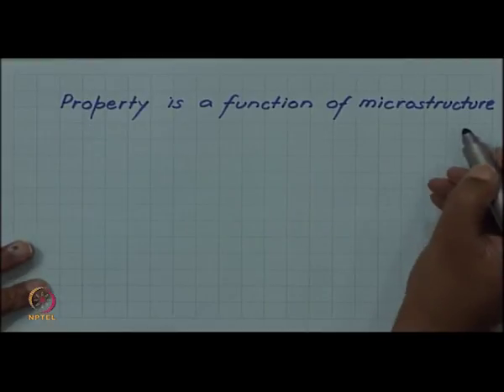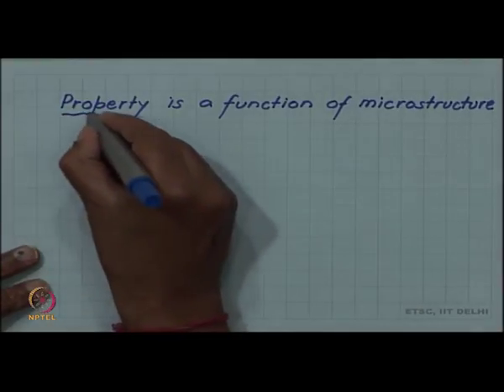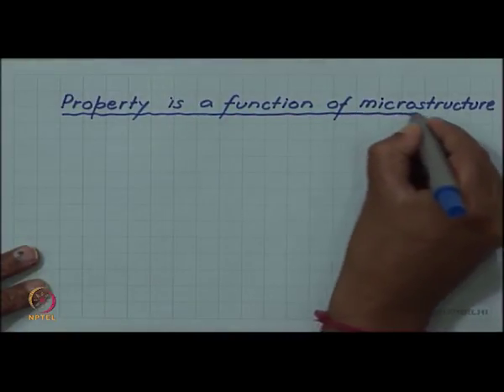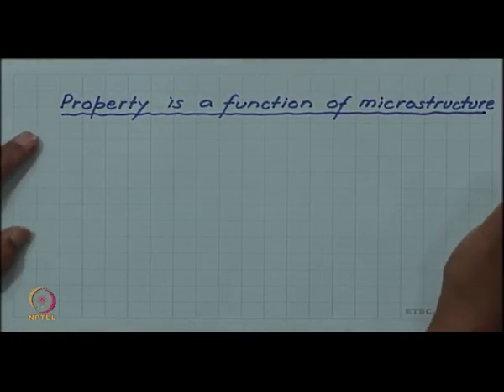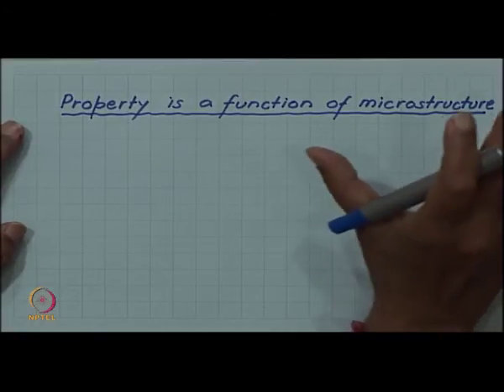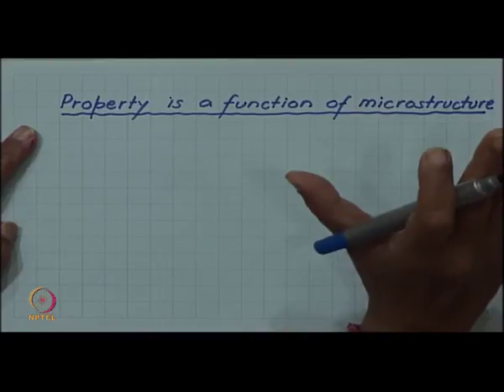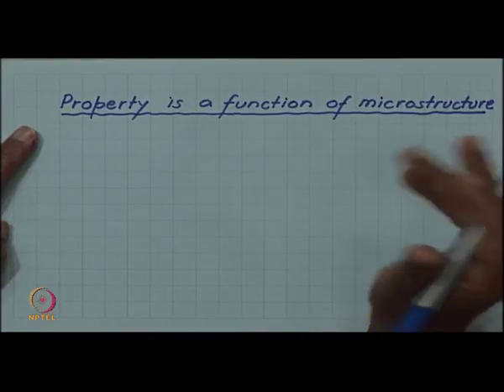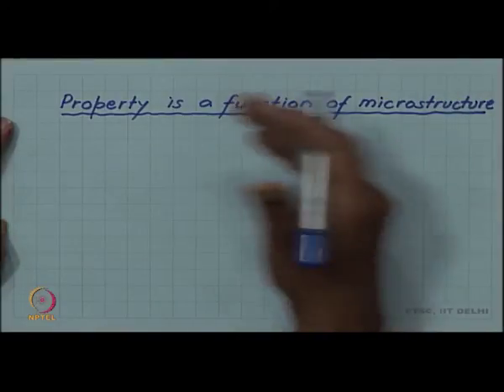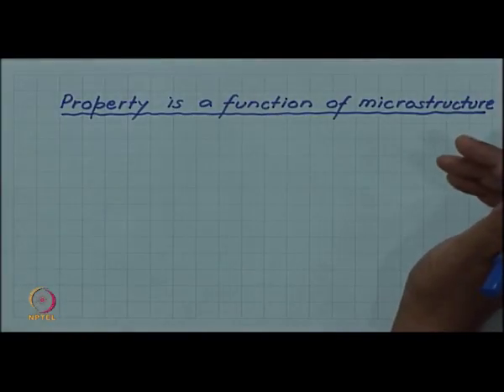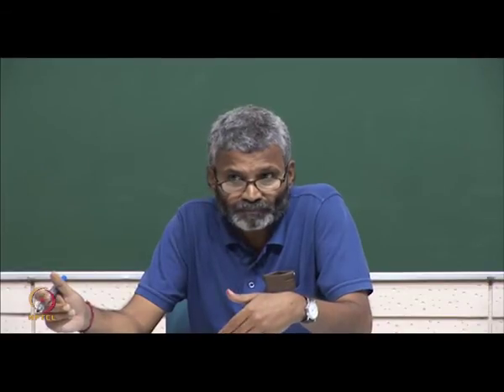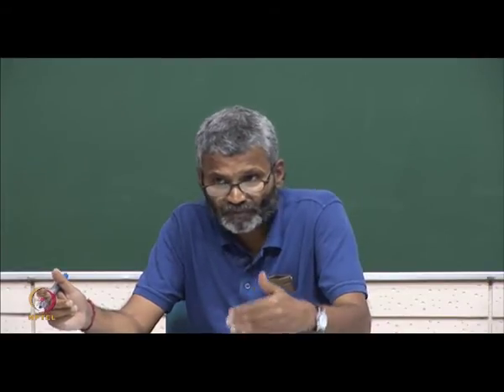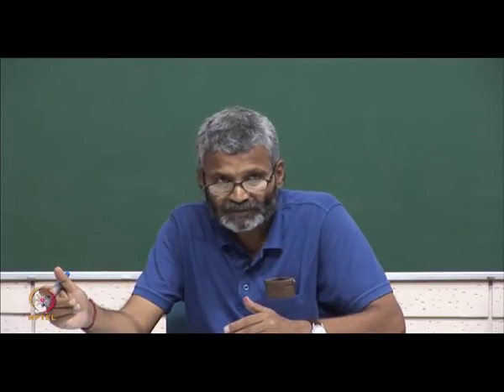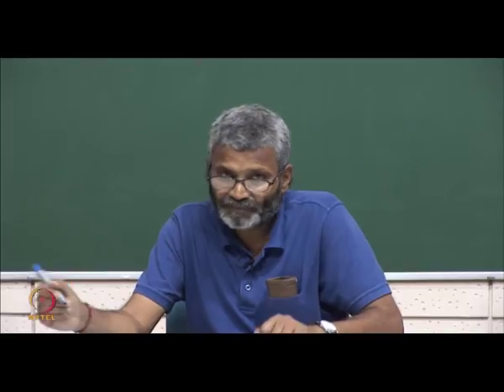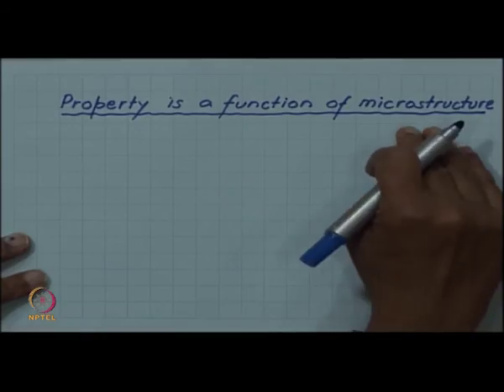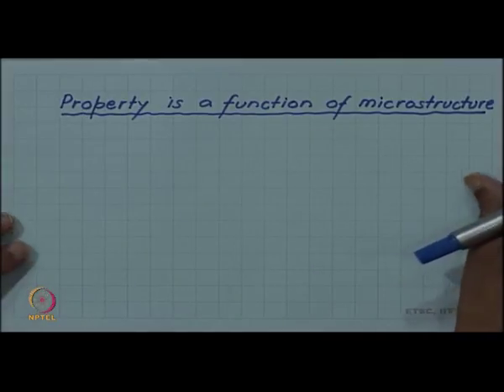So, first of all, property is a function of microstructure. This is our main theme in the material science course, and we have seen this very nicely in particularly in the microstructure and property of steels. We saw that in the same steel of 0.8% carbon, for example, we can get hardness values in the range of a factor of 4, we can get a hardness of 15 Rockwell or a hardness of 65 Rockwell simply by controlling the microstructure. So, microstructure is an important determinant of the property in the steel of same composition.